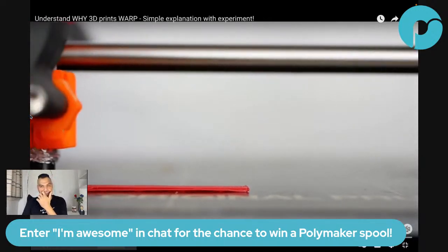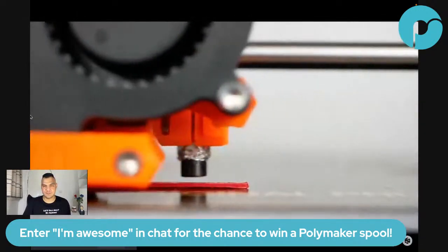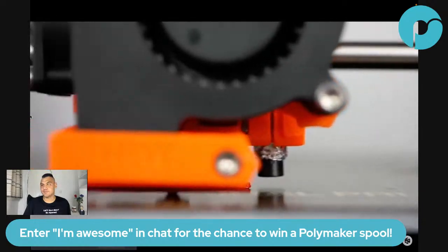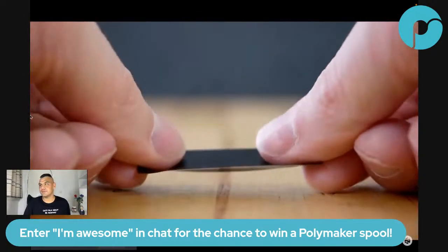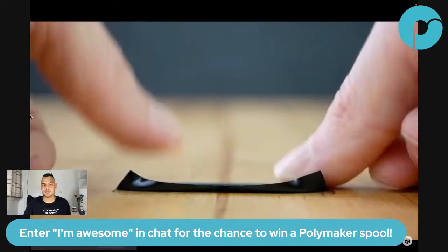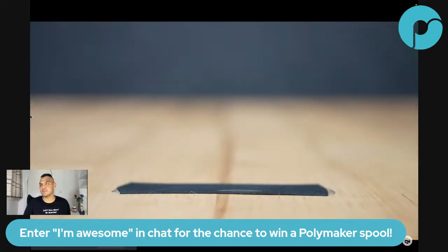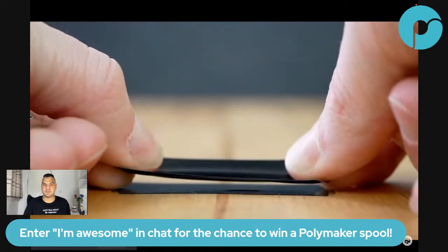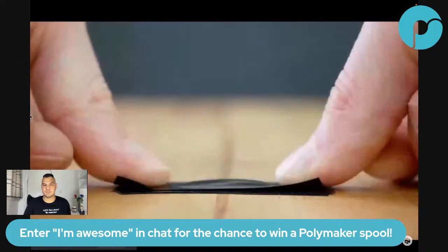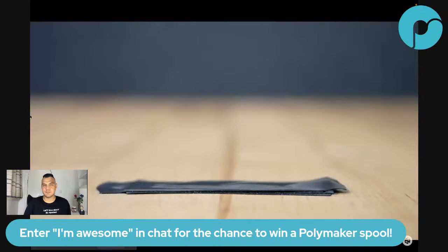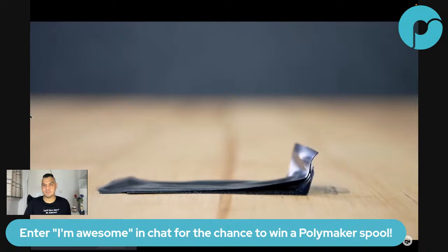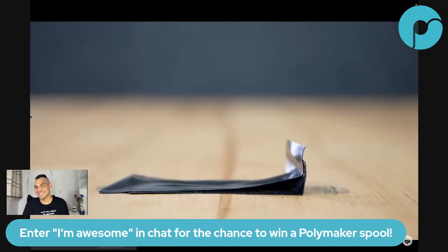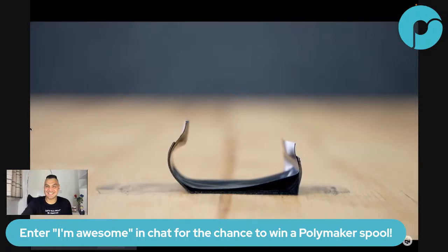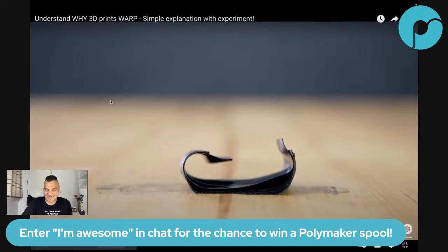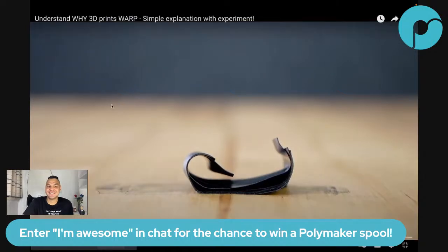Our 3D printing materials are mostly extruded at over 200 degrees Celsius and then cool down and solidify, which makes some shrink quite a bit. A piece of tape represents a layer that is printed. I simulate the material shrinkage by pre-stretching it and then sticking it to the table. Every subsequent layer will now pull on the lower layers. At some point, the connection to the table is not good enough anymore, and our simulated 3D printed part releases from the table and warps. There you have it. This is why 3D prints warp. How you can prevent this phenomenon is a topic for another video. Give this experiment a try yourself and share the video with everyone.